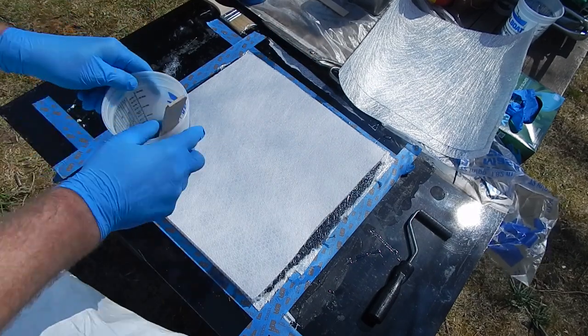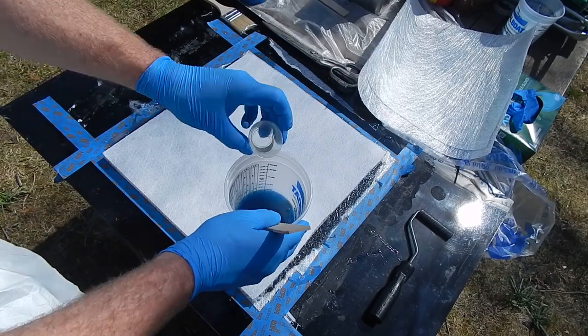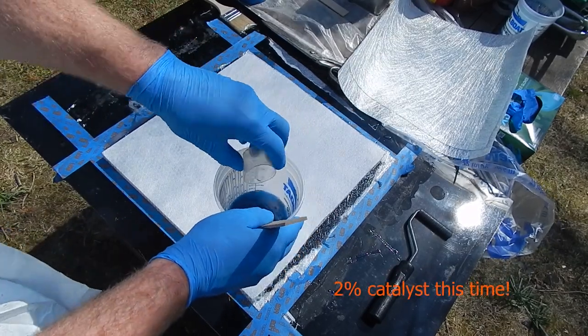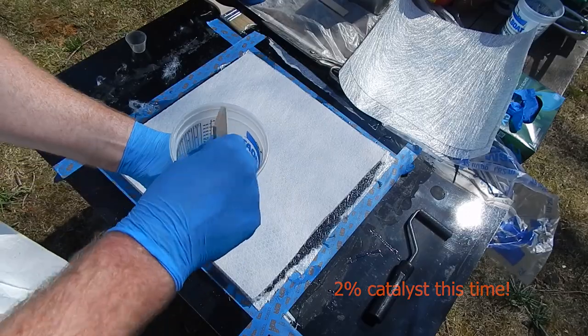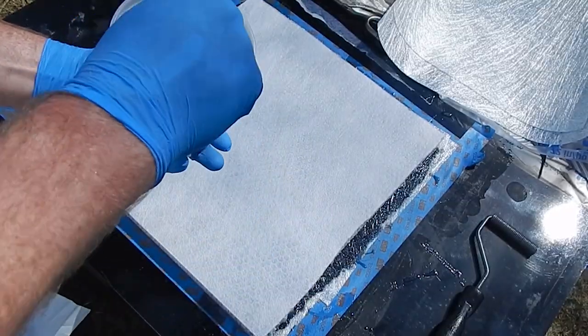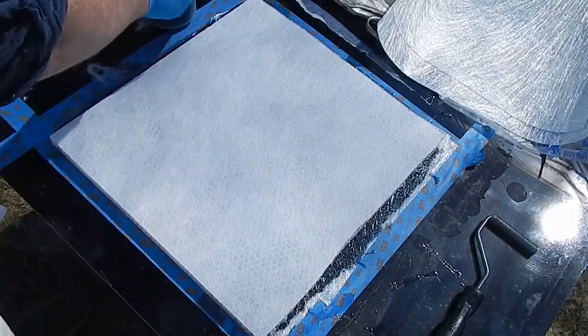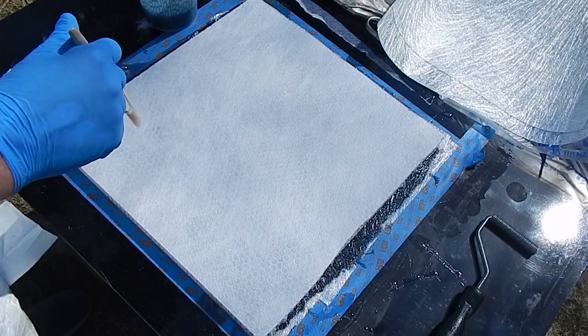And everywhere but in the very middle was pretty ugly. So this is why shot bags, vacuum bags, things that apply a more relative pressure as opposed to just a big chunk of metal that really only hits the high spots.